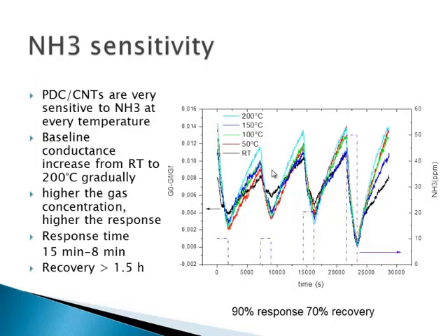Here you can see with the temperature, the behavior is exactly like a carbon nanotube. We don't change its property. It's still p-type response. With the temperature, we didn't change it that much, so the ammonia response doesn't change. So we have a little bit of increase in the sensitivity, but still, even at room temperature, you can still see the sensitivity.